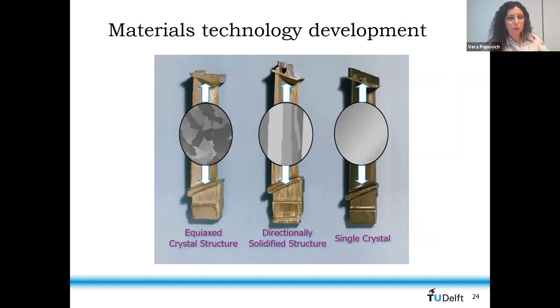I promised you guys to look into grain structure. When we look into the materials, besides the chemistry, what is important is what the structure of the material looks like. If back in, let's say, the 50s, the materials were produced with conventional casting or even wrought materials, the grain structure was mostly equiaxed. As you can see, these are relatively small, equiaxed grains.